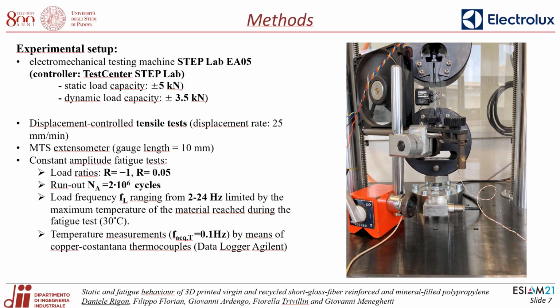It was 30 Celsius degrees, and the temperature measurements were carried out at frequencies of 0.1 Hz by means of copper-constantan thermocouples by using a data logger.